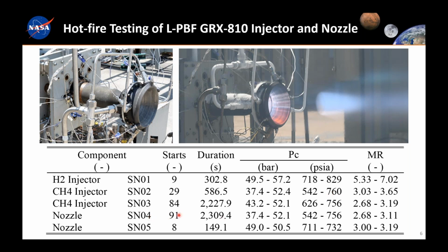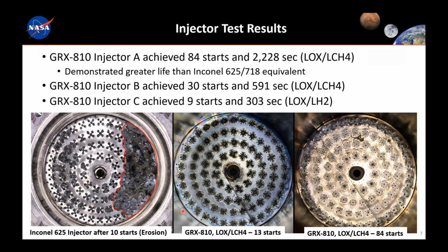And one thing that I want to note in particular here is these injectors and nozzles. The injector that saw 84 starts in over 2,000 seconds, and the nozzle that saw 91 starts. And those are both important to us because when we compare to some of the more traditional materials that we've used for injectors, such as Inconel 625 or Inconel 718, you can see in the bottom left there that we would typically see erosion on these injector faceplates after about 10 starts. And with one of our injectors in GRX 810, we've made it to 84 starts. So we're seeing improved service life on the GRX 810 material as well.